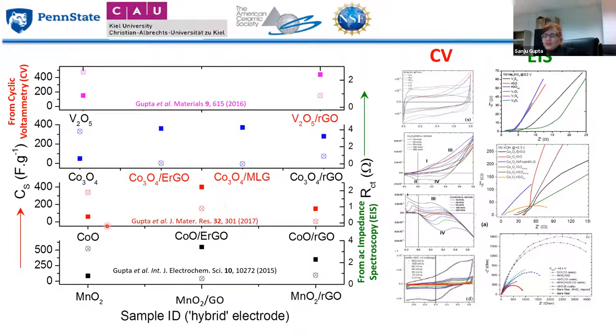So this is basically a summary of these graphene-based hybrids with the transition metal oxide. This also includes the results from vanadium pentoxide. And then we published all this work in different places. And this is the charge transfer resistance determined from the impedance spectroscopy and so forth. And we actually utilized this as one way of probing the structure of the electrode-electrolyte interface using, as I said, scanning electrochemical microscopy, which not only determines the electron transfer rate, but also images or maps the electrochemical activity.